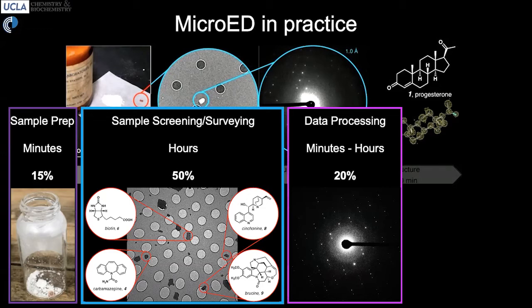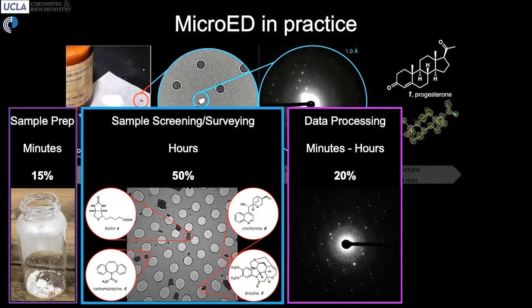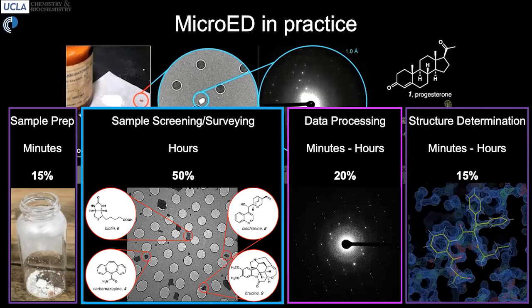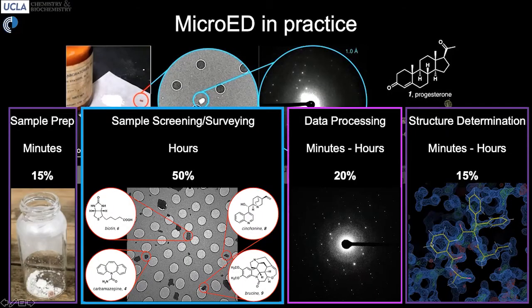So you'd convert those movies into some kind of format that is understandable by conventional crystallographic processing software packages. And we use a variety of software packages to do this, but our favorite is one called XDS. So XDS would take in these images. It would identify the type of diffraction that you have as crystalline diffraction, and then determine lattice parameters that gave rise to that diffraction, given the geometry of the experiment in the electron microscope. Ultimately, it would give you a set of intensities that, when transformed by a phasing program or a structure solution program, would actually give you density, a representation of your molecule in real space that you could then model using a modeling program and place atoms into. So that's the overall strategy.